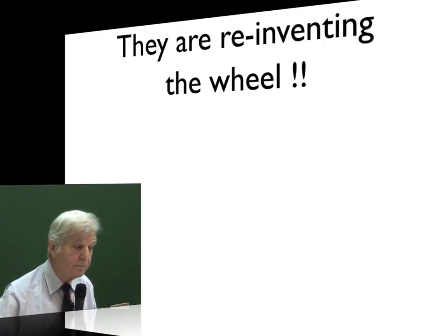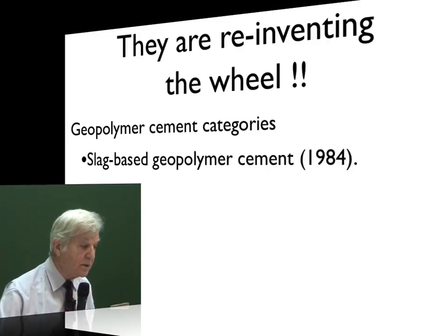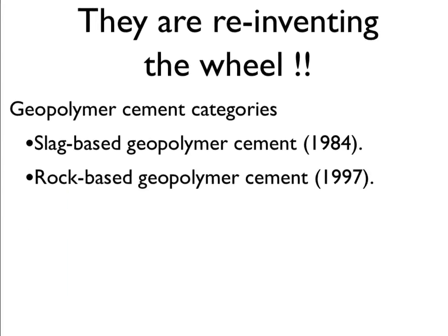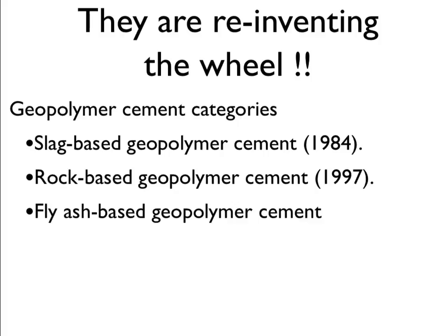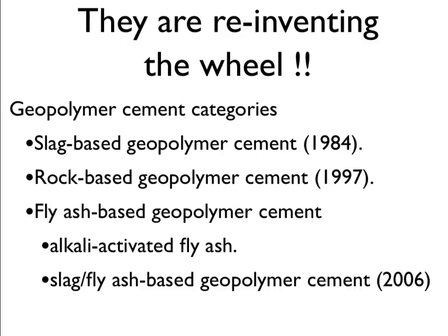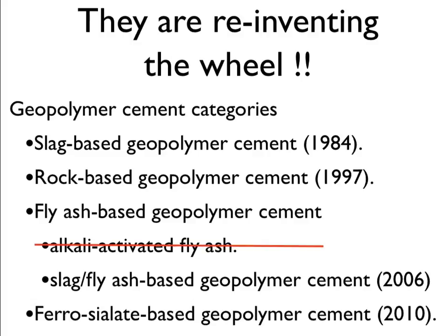From the beginning, we have the geopolymer cement categories. Slag-based geopolymer cement was invented by myself in 1984 when I was in the US. That is 30 years ago. We don't need these guys to know what we have to do. Rock-based geopolymer cement, so we decrease the amount of slag, we decrease the amount of alkali needed, was invented in 1997. We had a European research project with 6 geological institutions to do this. Fly ash-based geopolymer cement is something that is, well, alkali-activated fly ash, forget about it. Slag fly ash-based geopolymer cement, and ferro-sialate-based geopolymer cement 2010.